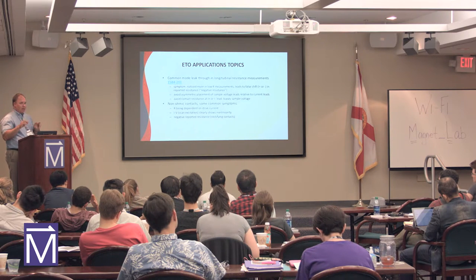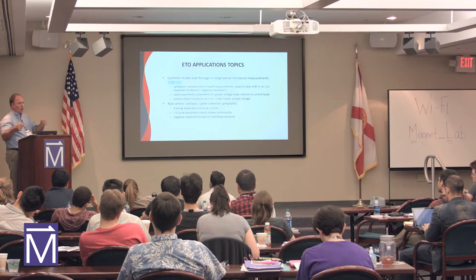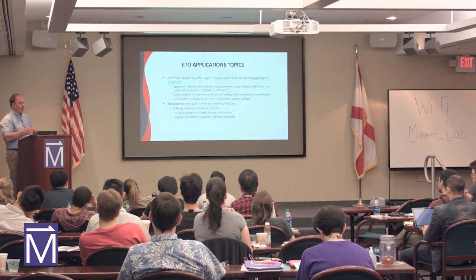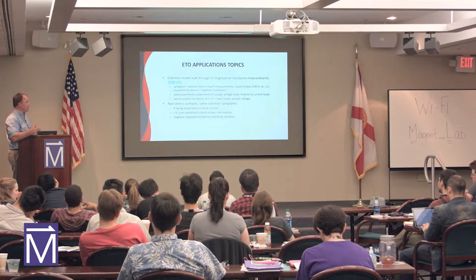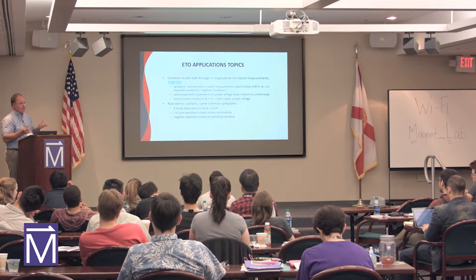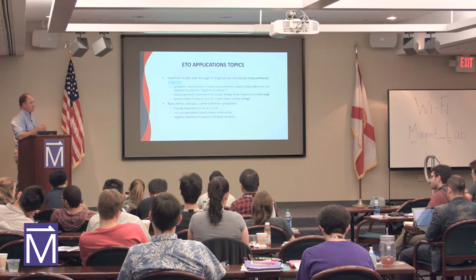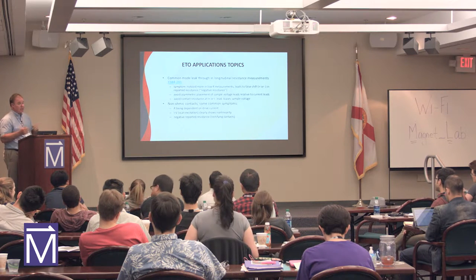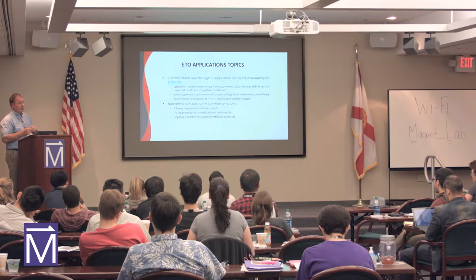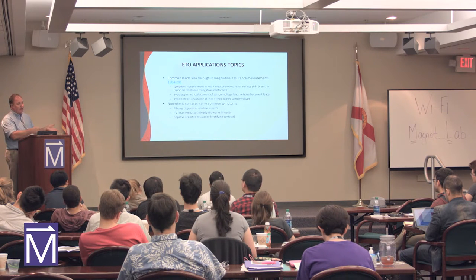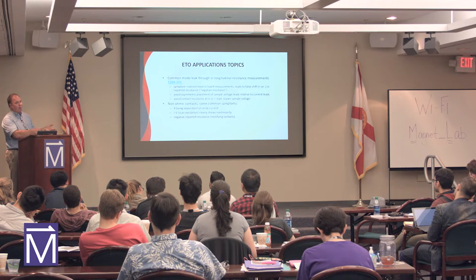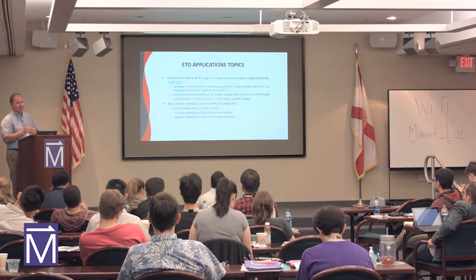So you want to have your leads on your sample so that they're symmetric on the sample. You wouldn't want to put leads close together on one part and farther apart on the other part of a sample. And then contact resistance is going to give you these false readings on the sample. So it goes back to how do you mount your sample, right? Everything's pointing back to sample prep, putting leads on your sample, mounting it on that.